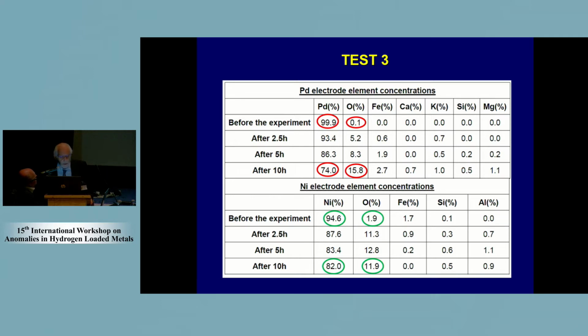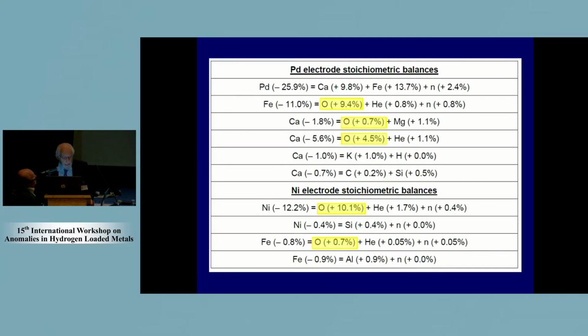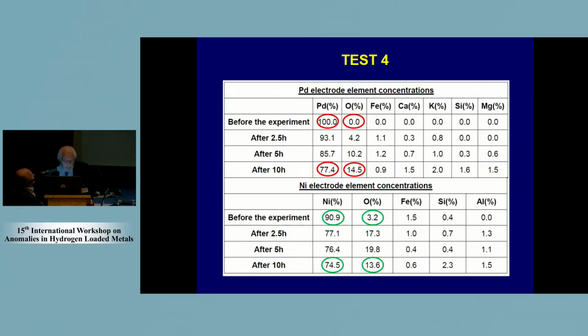I can read not only the numbers, of course, we have these red circles emphasizing the most important. You see that there is not an excess of potassium. And it's very important to observe that potassium is the main element in the solution, potassium, also oxygen, of course. And then we have the same kind of reasoning with this approximation in yellow evidence.